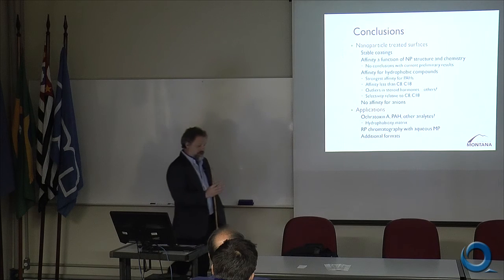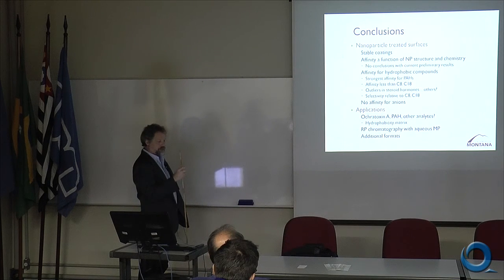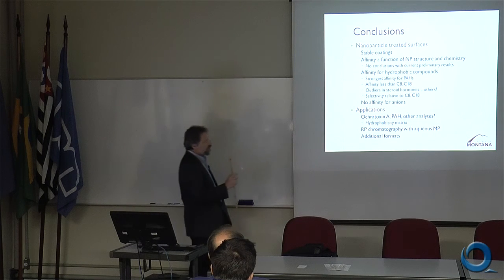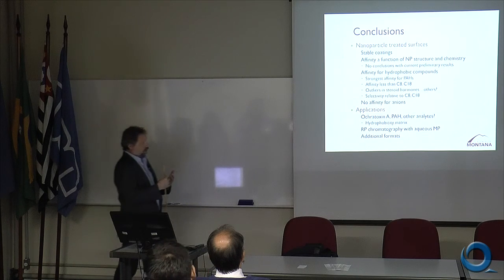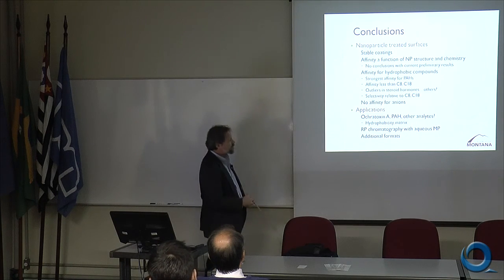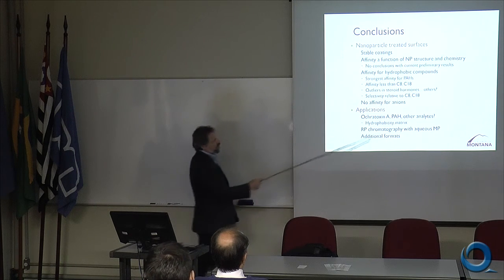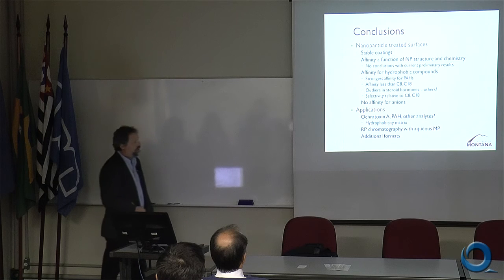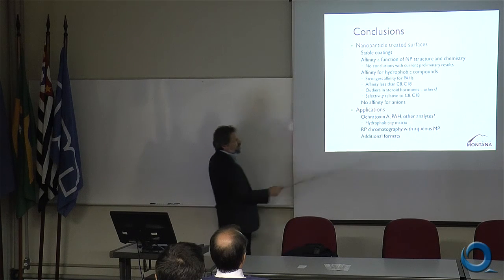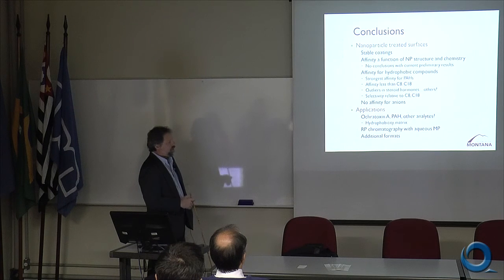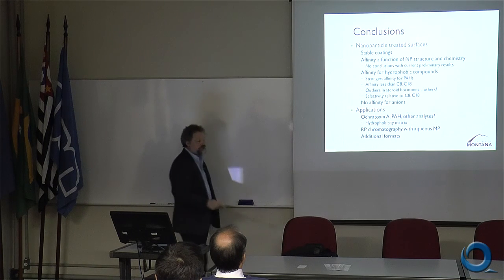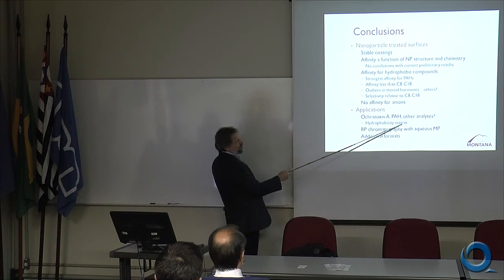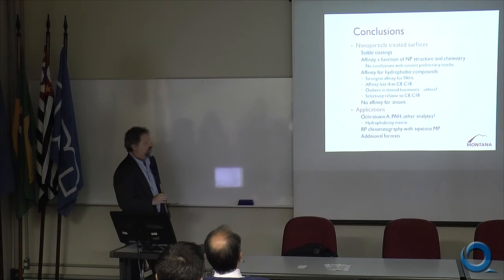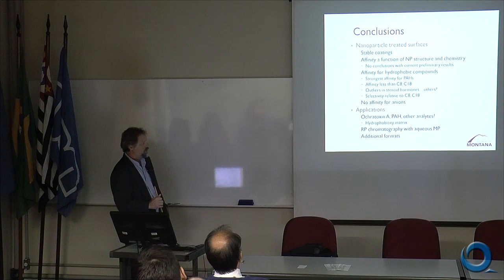So again, the reason for that is not entirely clear. It could be because we have a lot of bare silica, which is also anionic at those pHs, or it could be that the cationic functionality is really not accessible to our analytes. Applications, I think there's some potential there for the ochratoxin A extractions, certainly some potential for PAHs because we have strong interactions with those. We know that hydrophobicity is going to be a major factor in determining the extractability or the affinity, and that brings us back to matrix. We haven't done any experiments with different matrices besides aqueous matrices.